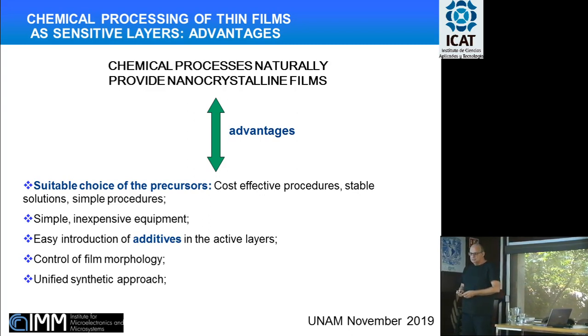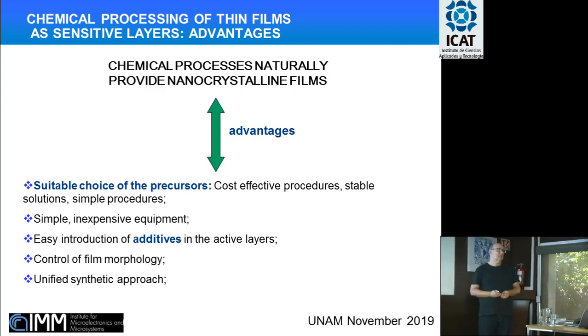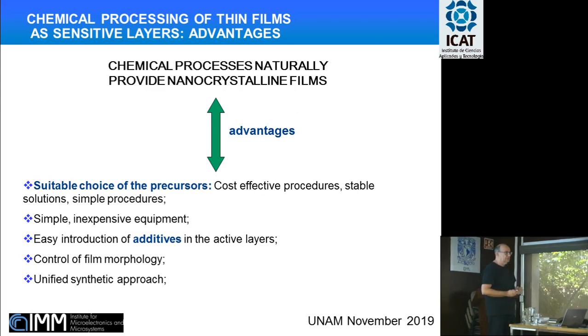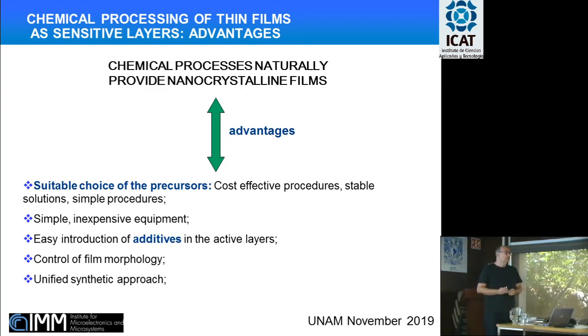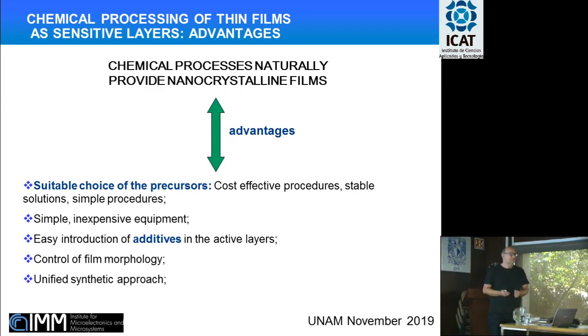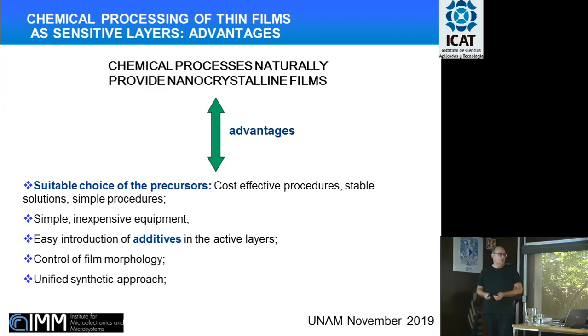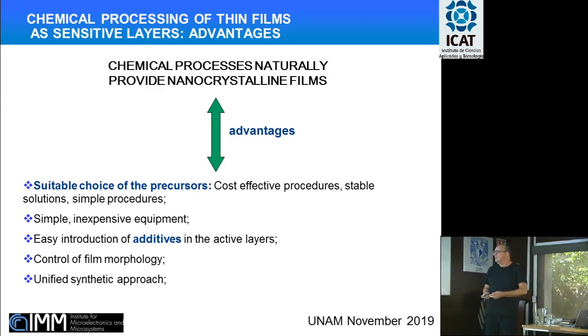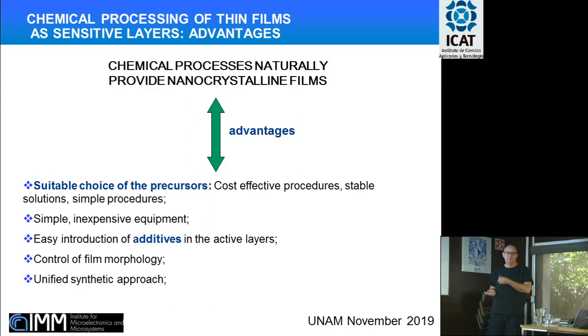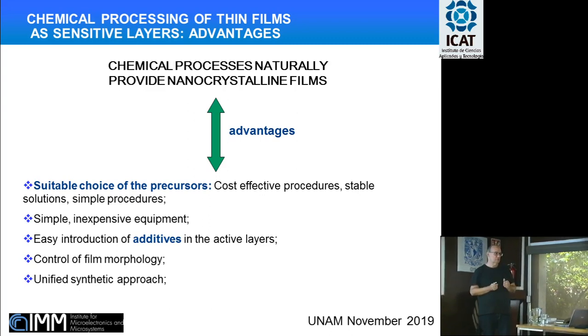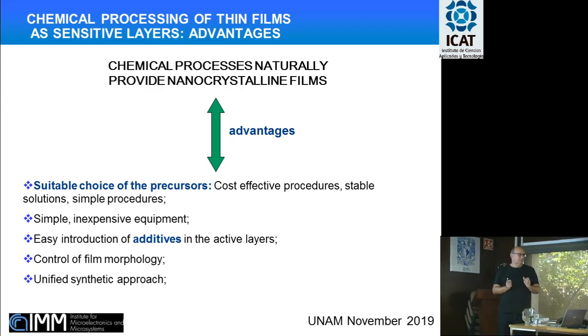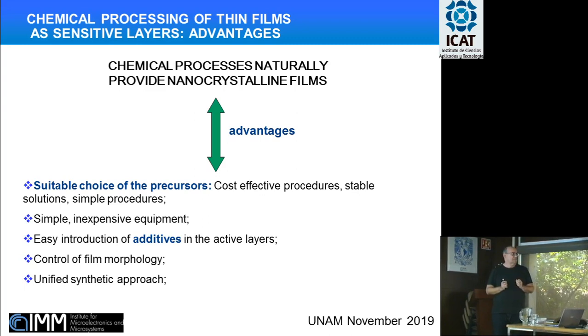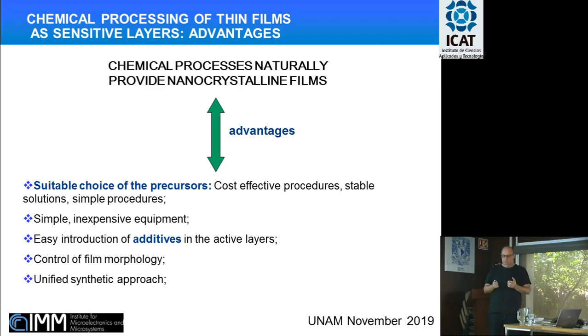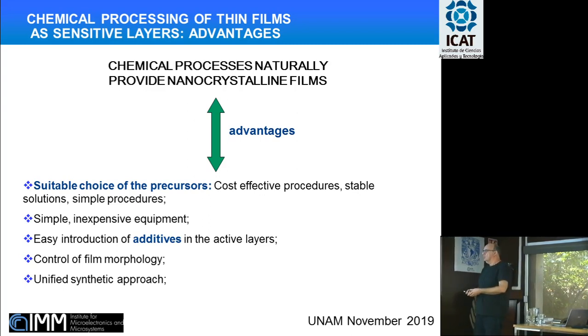So, the first application we tried to develop was the synthesis of thin films, because the historical activity of the Institute was mainly focused onto the synthesis of thin films. So is it possible to prepare nanocrystalline thin films? If this suggestion that nanomaterials can improve the performances of chemoresistive gas sensors is right, then why not begin with the synthesis of nanocrystalline thin films? And from this point of view, chemical processes naturally provide nanocrystalline films, simply because there are many, many nucleation points in the film when you do the synthesis. So the mass transport of the material during the heat treatment process for crystallizing the material is limited to very small zones. Basically, this results in the creation of small grains.